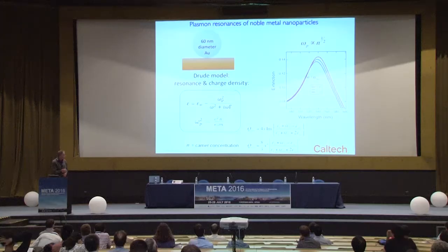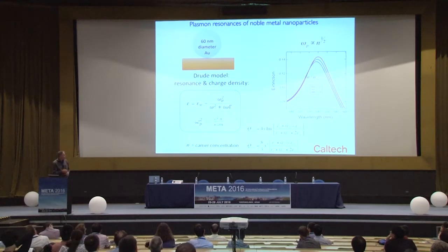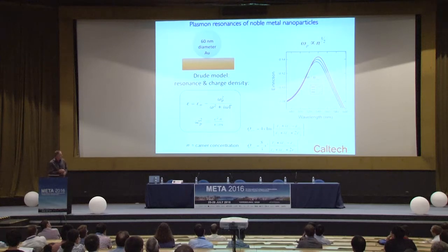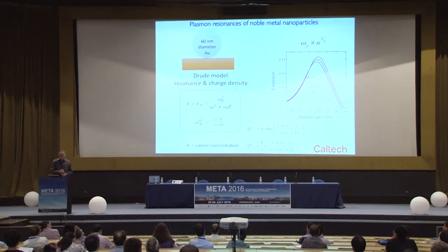So the simplest kind of optical antenna that we could make would be just a metal nanoparticle. And if we think about the opportunities for tuning the extinction of a metal nanoparticle, if we take the same Drude picture for the permittivity and look at the extinction, we can see that if we were able to change the carrier density in this metallic nanoparticle by a few percent, we could tune slightly the resonant frequency and the extinction of a metal nanoparticle, just from very simple considerations.